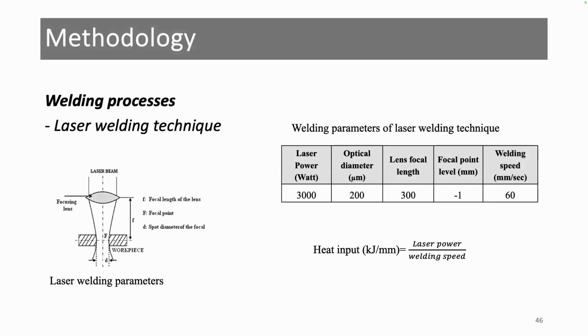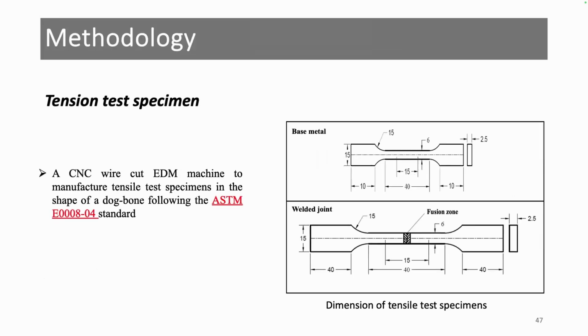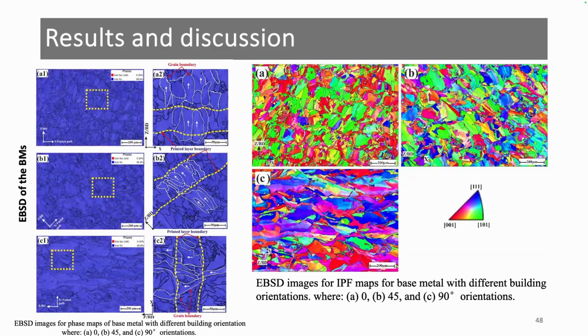While for the laser welding, we were using this parameter for the welding processing. So the heat input for laser was about 0.05 kilojoule per millimeter. Here is the dimension of the tension test specimens. And now we go to the results and discussion of this study.